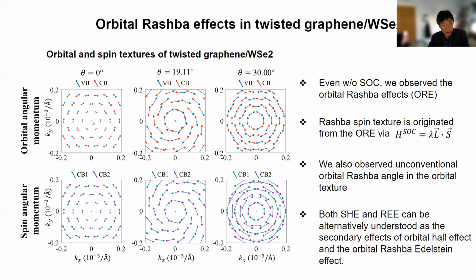The orbital angular momentum here refers to the px and py orbitals. In the case of pristine graphene, we know that it is described only by the pz orbital. But in this case, because of the bilayer structure with TMD, you also have a finite px and py orbital content, and that can also have an orbital texture, and we see a very strong similarity between the orbital texture and the spin texture. I'm not going to go too much into this, but basically the origin of the spin texture that we see here can be traced back to the orbital texture.